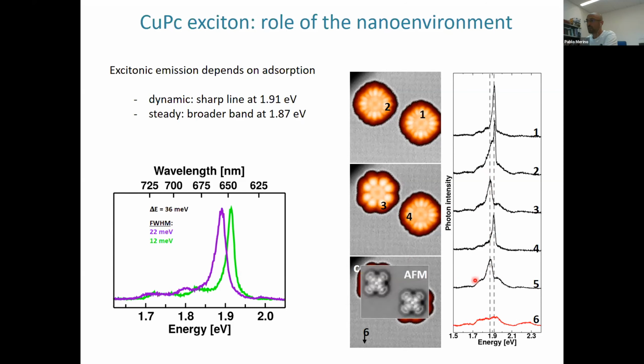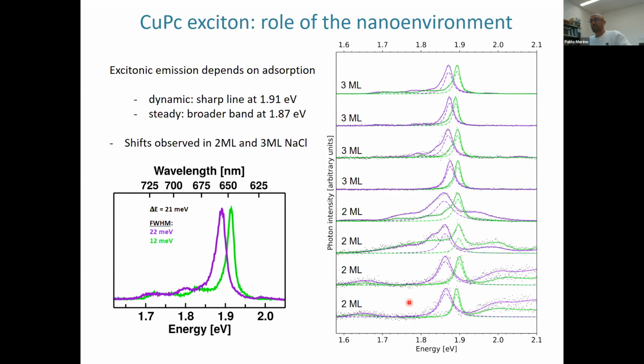And actually, we can again take AFM images and really tell that these molecules are stabilized. And this effect is quite robust. Okay, the energy may vary by a few millielectron volts from molecule to molecule, but the change between dynamic and steady is very robust. And I show here 8 different examples for 8 different molecules on 2 monolayers of salt and 3 monolayers of salt.